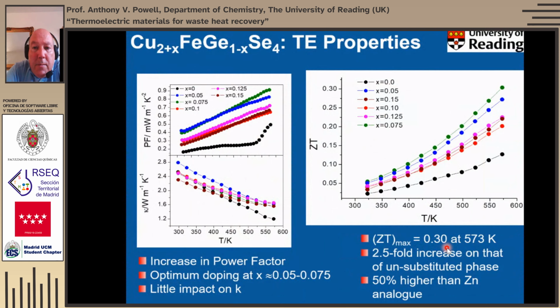So the net result is that we now get up to a figure of merit that's about 2.5 times that of the unsubstituted phase, and significantly, in view of the fact we were trying to get an improvement as a result of a magnetic ion being here, about 50% higher than that of the zinc analog. So we're up at about 0.3, but I would stress at quite low temperatures, at 300 degrees centigrade. So it's quite useful for industrial waste heat type application.